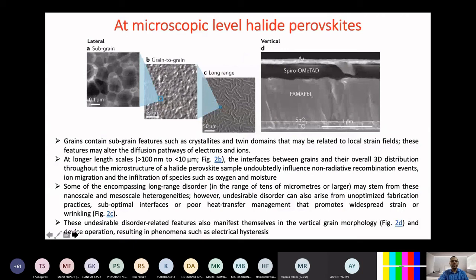So these are on very different length scales. You are looking at 50 micrometers. If you further zoom in to the 2 micrometer scale, these ripple-like stretches look like this. And further, going from 2 micrometers to 0.1 micrometer, you find further structure inside the perovskite. So this is what is shown.